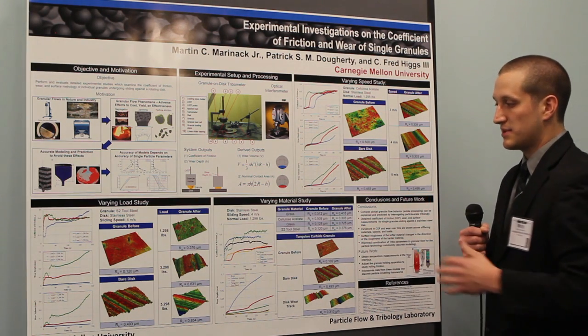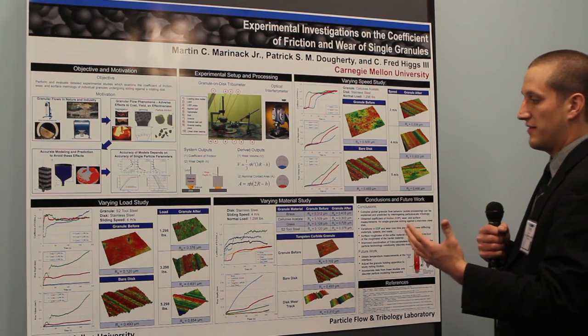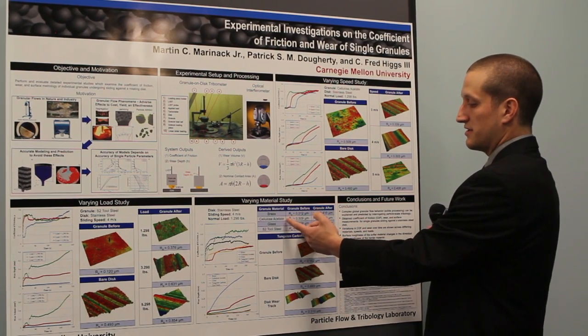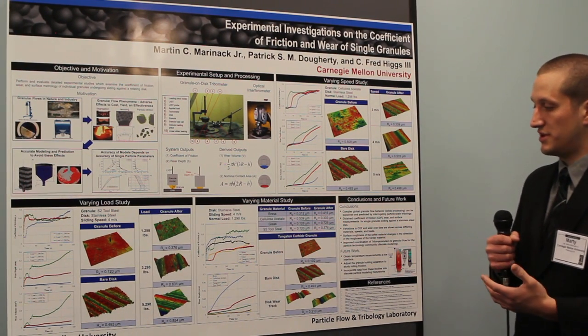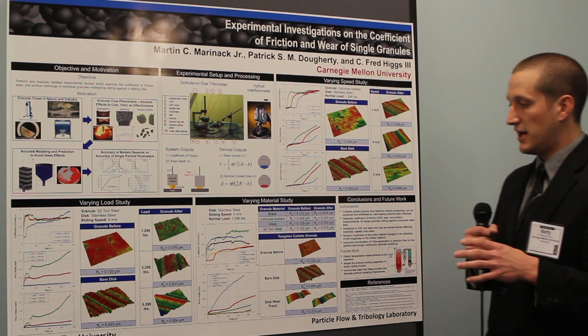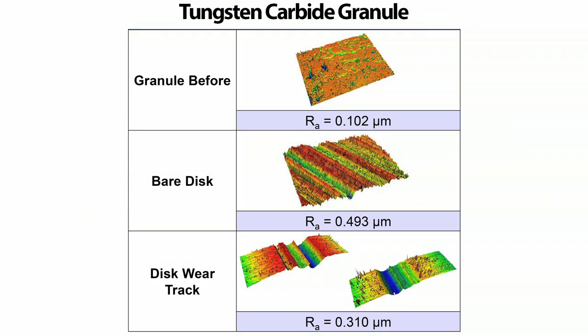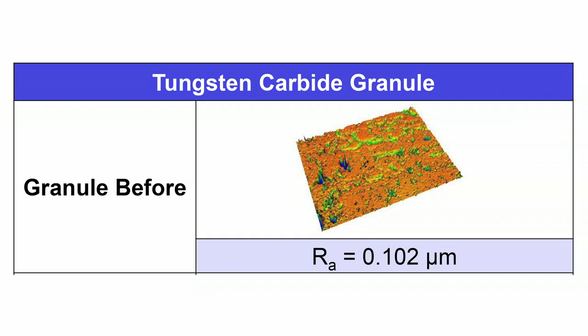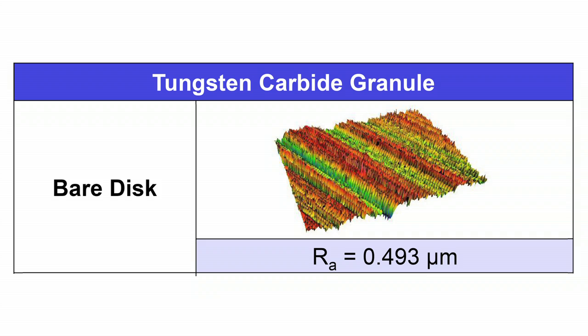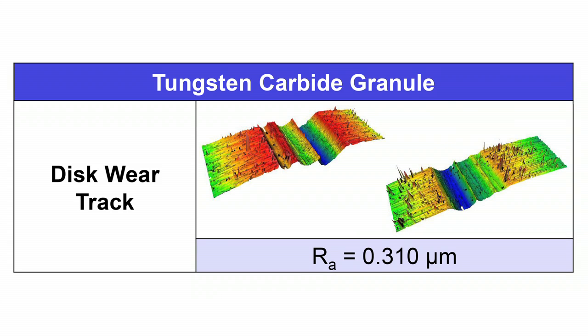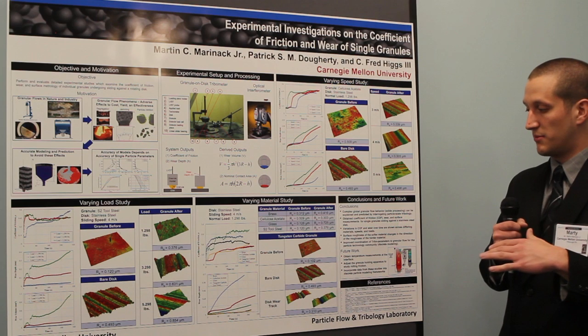What I show here in the next box is all the different materials that we studied. We studied five different granule materials, those being brass, cellulose acetate, glass, tungsten carbide, and a tool steel material. What I'll highlight here is the tungsten carbide granule. This study was unique because this was the only study in which the disc wore as opposed to the granule. And what we saw here is that the granule initially starts out much smoother than the bare disc. And as the disc wears, the roughness in these wear tracks actually becomes smaller, and so the tungsten carbide granule is actually causing the disc to become smoother.